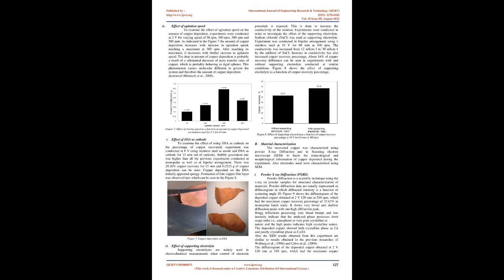The experimental results of copper recovery using two electrodes are shown in Table 3 and using four electrodes are shown in Table 4. In the first set, experiments were carried out from 1V to 4V at 510 rpm and are shown in Table 3. The maximum copper recovery of 32.62% was observed at an applied voltage of 2V for 120 minutes. Copper deposited on stainless steel was shiny in appearance.